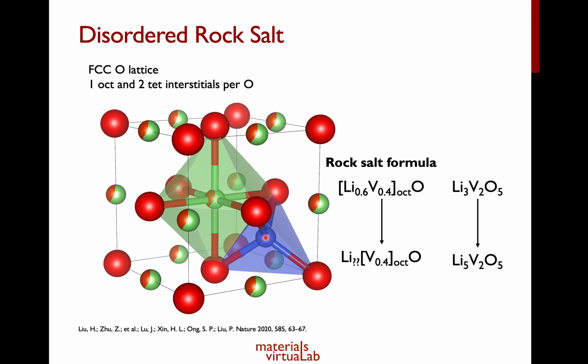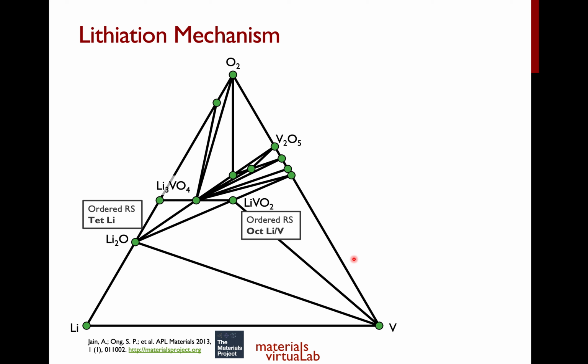Now, during the cycling of the disordered rock salt Li3V2O5, Haotong and Ping were able to cycle it between Li3V2O5 and Li5V2O5. So we know that basically we can get it up to about lithium 1. However, what we do not know is really what is the occupancy of lithium throughout this lithium insertion process, right?